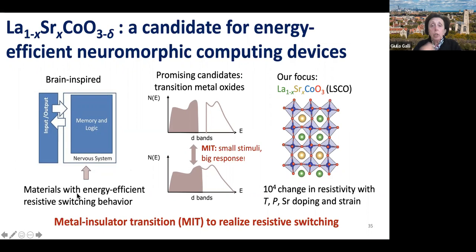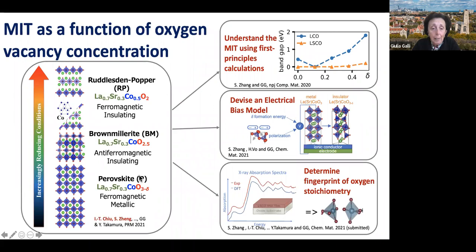And we have been studying a material, again, in collaboration with experimentalists, and again, building on experimental work, which is lanthanum strontium cobalt oxide. And the question here has been, can we induce a metal to insulator transition by changing the content of oxygen vacancy in this system, this delta here? And this is a summary of the whole work. So we have looked at different phases that the material exhibits as a function of oxygen vacancies. The names, perovskite, Brownmillerite, and so on, are listed here, not important right now. Just to say that there are different phases that the system has depending on the oxygen vacancy content.